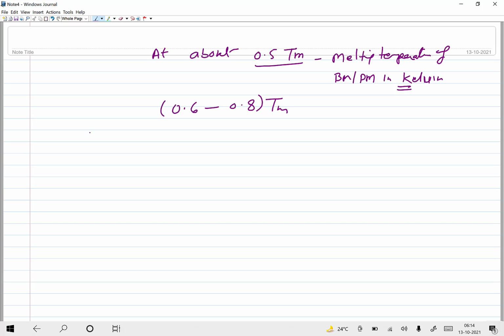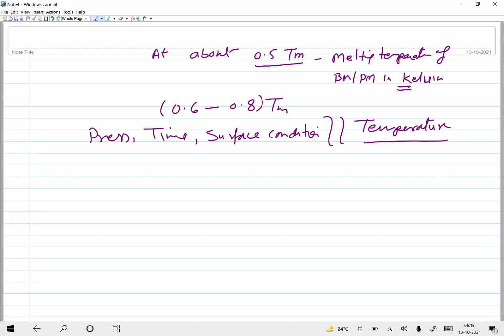Okay, in any case, depending upon the pressure allowed, the time in which the diffusion bonding is to be realized, and the surface preparation or surface condition of the bonding, the temperature must be established accordingly, so that a sound and good metallurgical joint can be developed. So indirectly, while establishing the diffusion bonding temperature, we must consider the pressure being used, diffusion bonding time, and surface condition, apart from the filler metal or interlayer, if anything like this is being used.